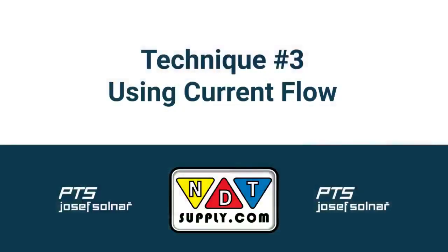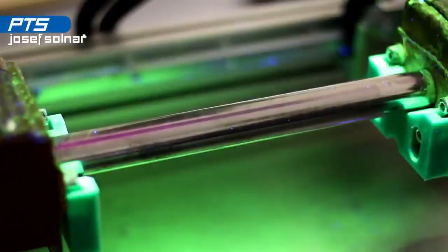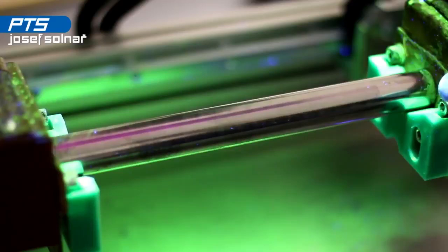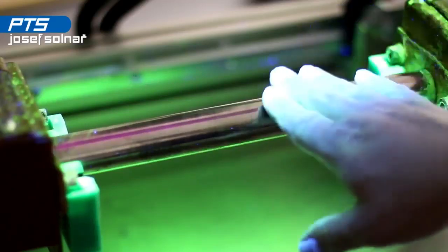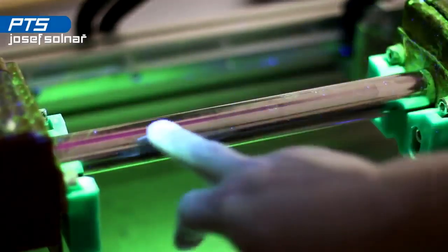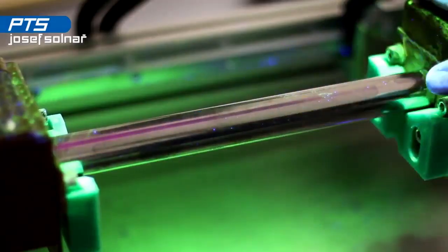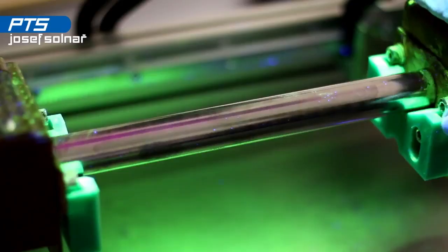Technique number 3, using the current flow. Another magnetic particle method is the current flow technique. With this method, electric current passes through the test piece, creating a circular magnetic field which allows detection of longitudinal defects. Place the test piece on the V-block supports, lock the tailstock, and clamp the part with the clamping lever